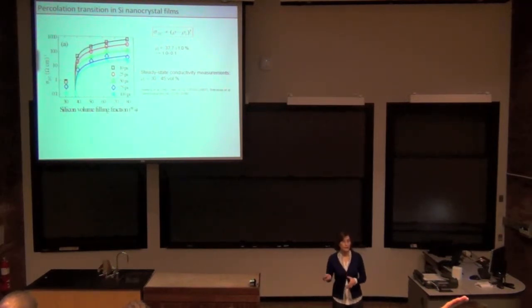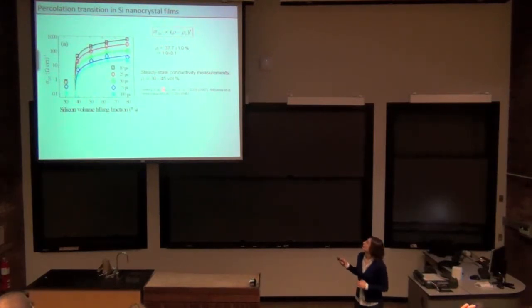So when we do that and plot at different times, we plot this DC conductivity as a function of only the infilling fraction. What we get is described very well with a very well-known percolation transition. So what we are observing is actually percolative transport above some sort of threshold of the filling fraction. And in turn, we are getting a percolation threshold at about 38% silicon, which agrees quite well with the photoconductivity measurements done in steady state.